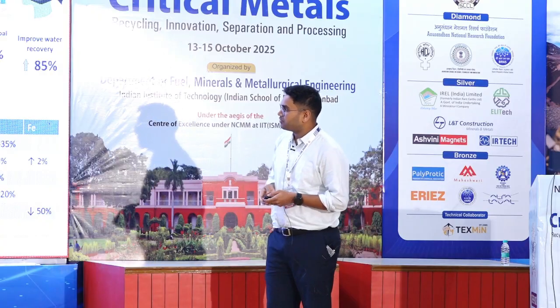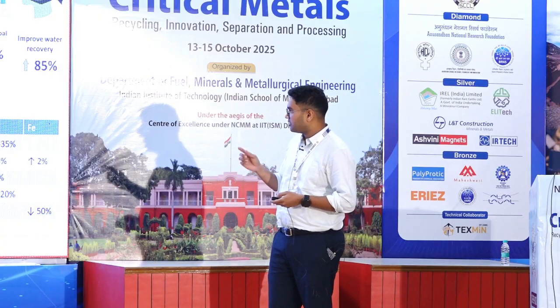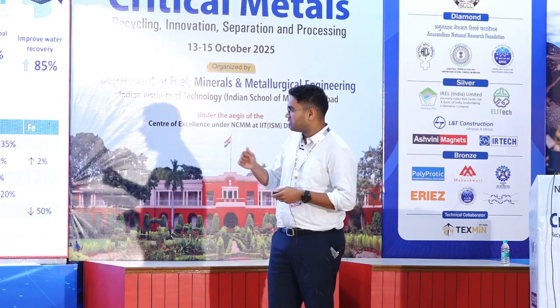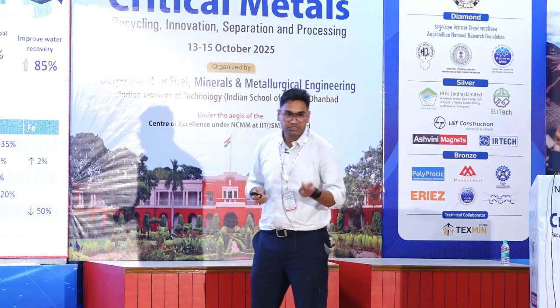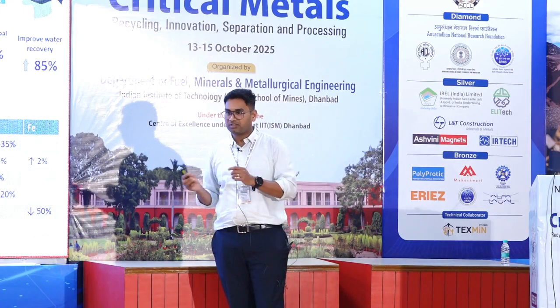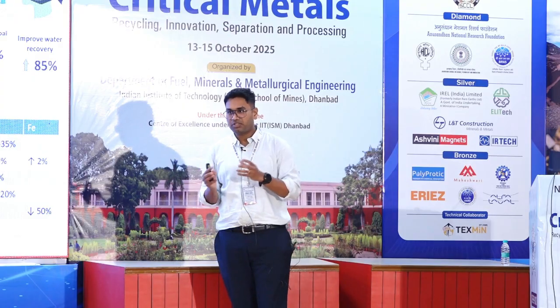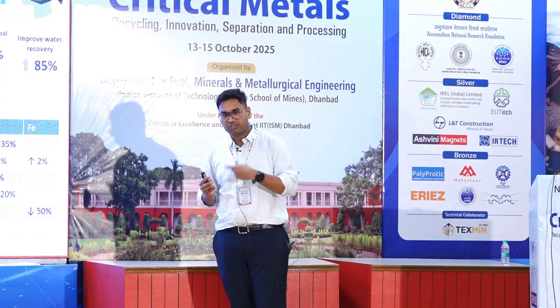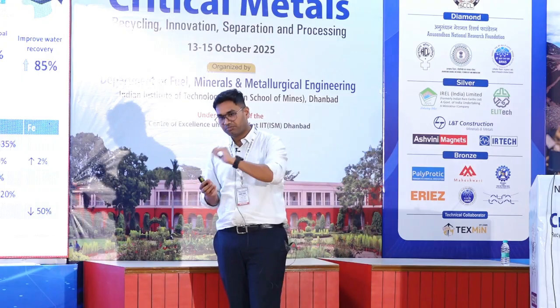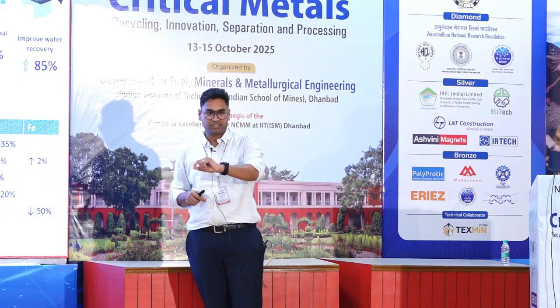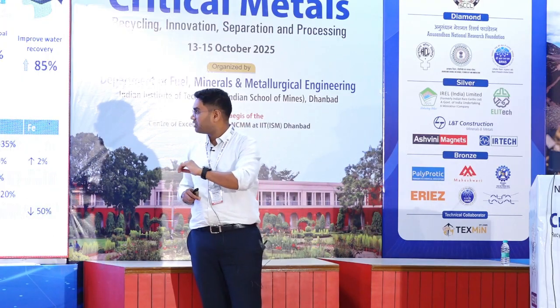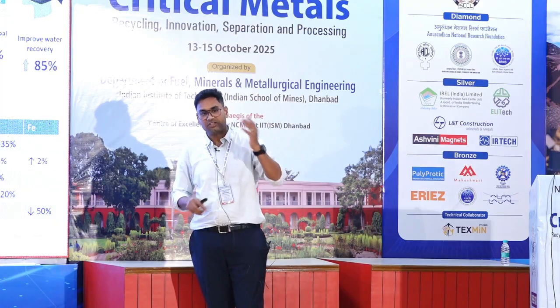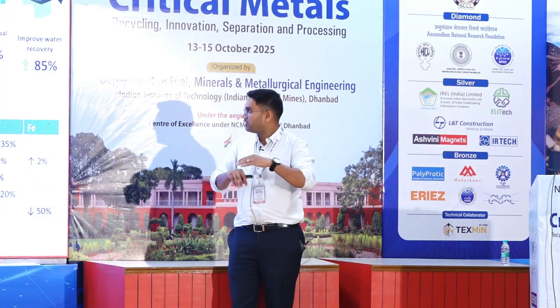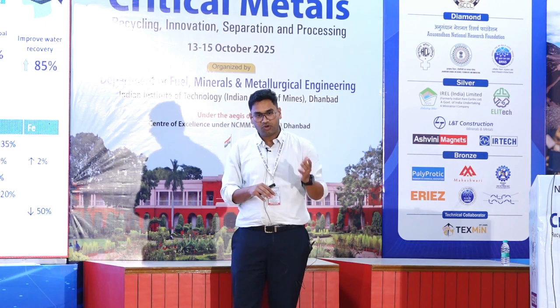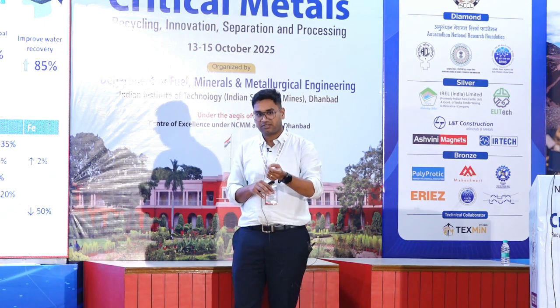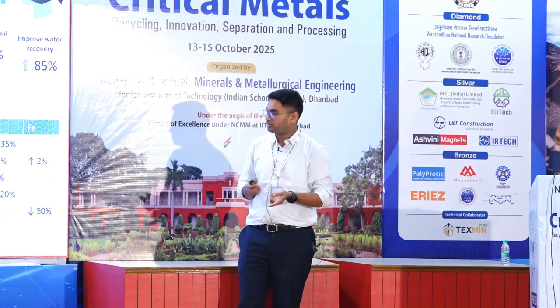Other advantages of using hydrofloat is that it can float even 1% liberated particles, because the bubbles are generated along with the feed itself, and therefore these bubbles just attach to even 1% exposed particles. And if that happens, then you can easily float those very, very coarse particles also.